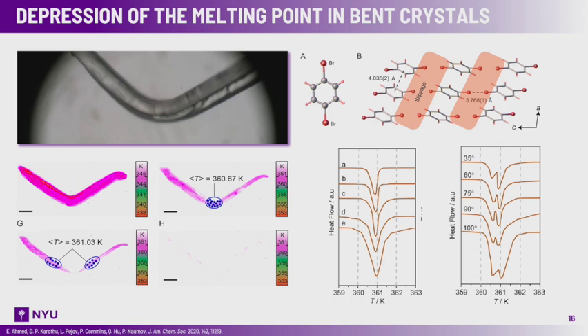Some side results of our research are shown here, where we found that if you bend a crystal, you decrease the melting point in the bent region. Melting point, being one of the most fundamental physical properties, is very difficult to control. But here, because of the increased amount of defects in the bent region, as you can see from the thermal images, we decrease it by a significant amount.